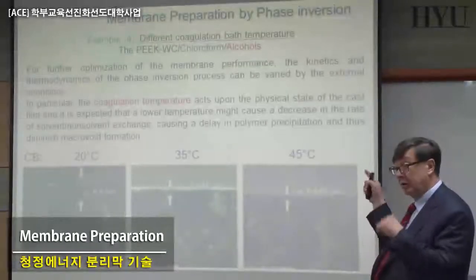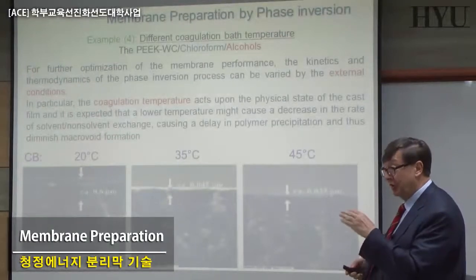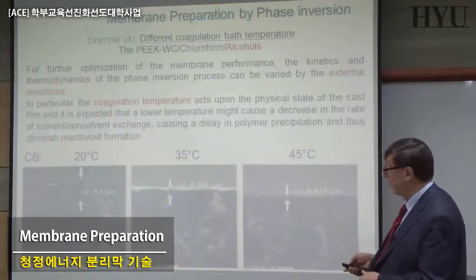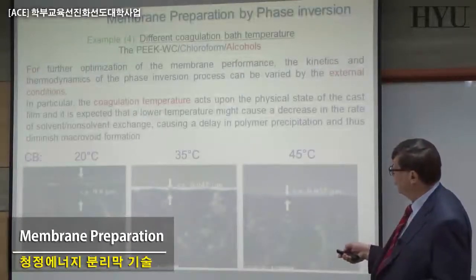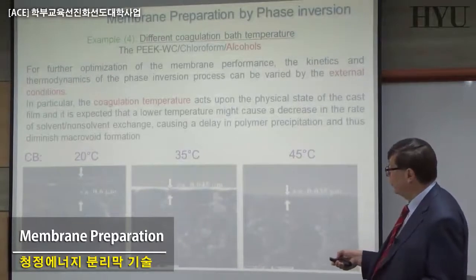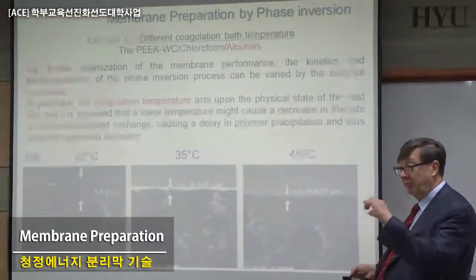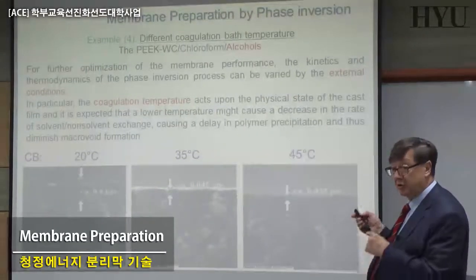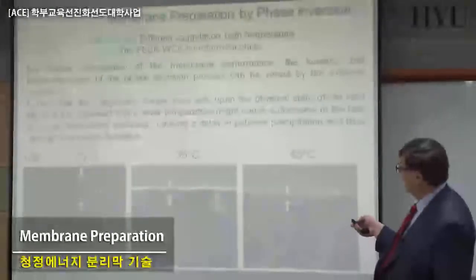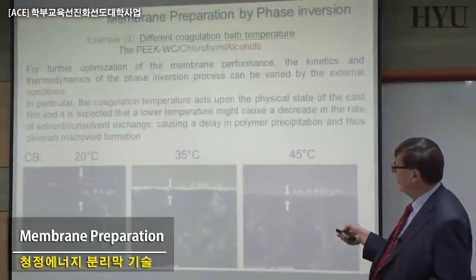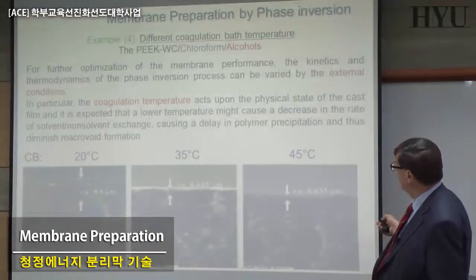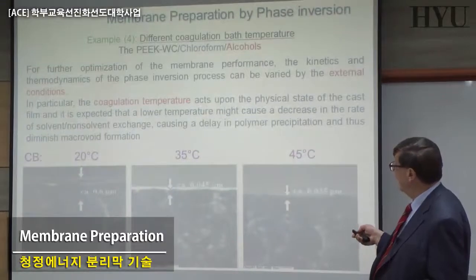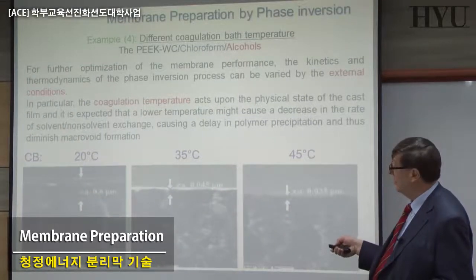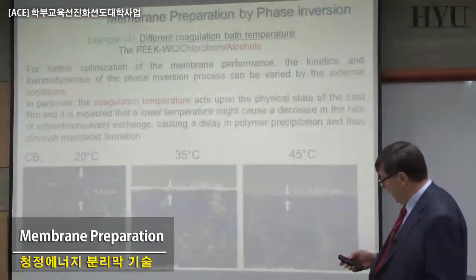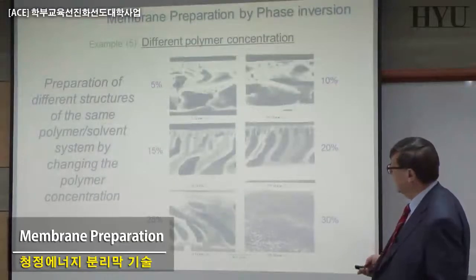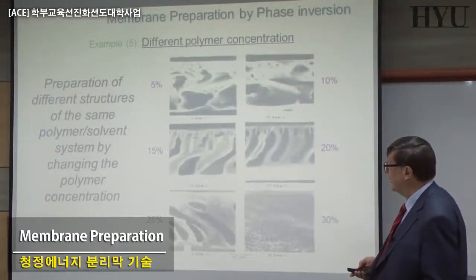Changing temperature, all these phase diagrams were at one temperature. Now you can change temperature, keeping constant concentration, kind of solvent, etc. And also here you can see you can just change from 20, 35, 45. You can go from 0.6 microns to 0.035 microns. You can decrease significantly the thickness of the layer. So it is another parameter for keeping control of the system. Coagulation temperature acts upon the physical state of the cast film, and a lower temperature, 20 degrees, is expected to cause a decrease in the rate of solvent/non-solvent exchange, causing a delay in polymer precipitation and decreasing macrovoid formation, etc.